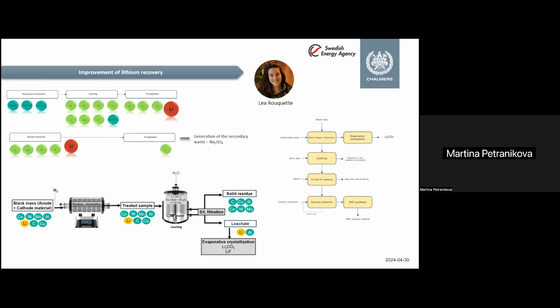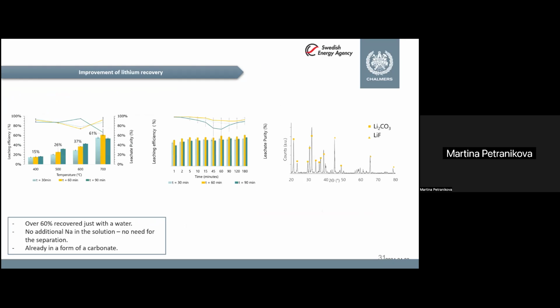And then also this is related to quite a large generation of the waste. So then the idea was to recover this first before everything. And what we did was a thermal pretreatment, because that's also what we have been working on for many years. When we do the thermal pretreatment, the pyrolysis, we can transform this lithium from lithium oxide and also from salts into the form of lithium carbonate. And lithium carbonate is leachable with the water.